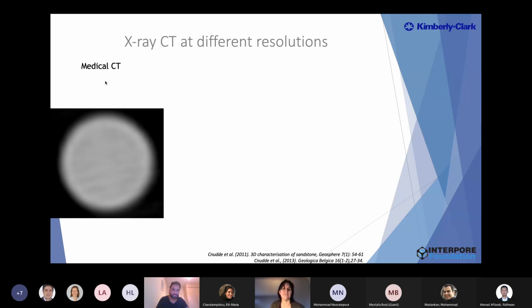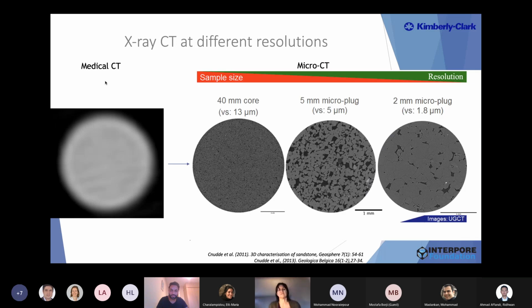That is why micro CT scanners were developed to go for higher detail. One thing about micro CT is that the smaller your sample size is, the better the resolution will be. So if you have a sample, for instance a core of 40 millimeters, it's no problem to reach a voxel size - and voxel is the 3D representation of what you know as a pixel in 2D, a volume element - a voxel size of 13 micron, meaning 13 by 13 by 13 micrometer, allows you to see these kinds of details.